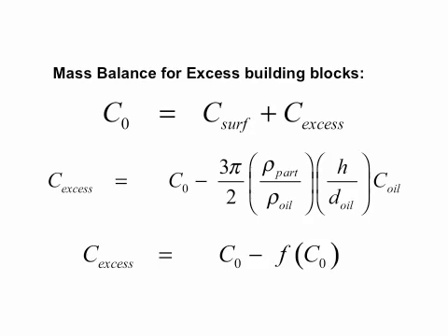If you do chemistry, you can always make a mass balance. You can basically say, okay, the amount of clay that I put in my system, C0, I go in grams per gram, right? Grams of clay per gram of water, because that's easier to measure. So forget about moles, because I've got objects here, it's a bit difficult. So just gram per gram, so it's a dimensionless concentration almost. That is the amount of clay platelets on the surface, plus the amount of clay that's in excess, and in excess, I mean, in this case, in the water phase.